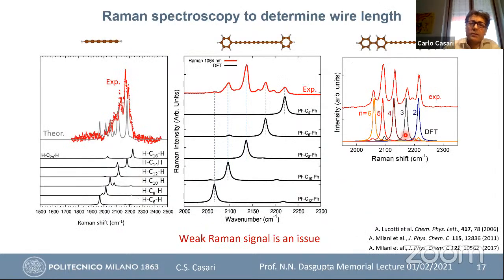But more than this, we are able to distinguish and to observe the different chain lengths in the sample. For example, in this case, from the experimental spectrum here, with the presence of different lengths in many peaks, by DFT calculations of the vibrational features, we are able to distinguish the different contributions of the different lengths. This is, for example, for hydrogen terminated chains, for phenyl terminated, for ones terminated by two phenyls, and so on. So Raman is very useful to observe and understand what kind of material you have produced.